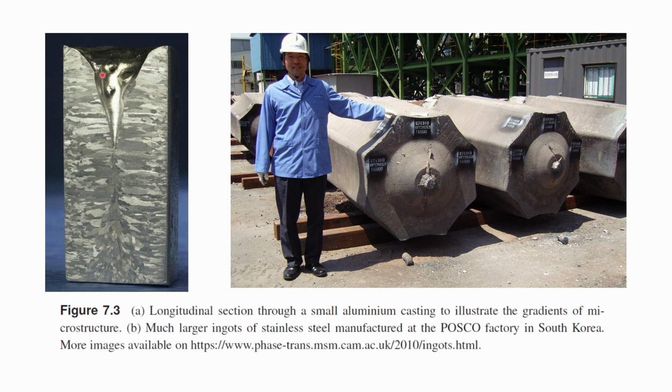The figure on the left here shows one example for aluminum materials, a product made by the casting process. You can see there are 3 layers roughly, and this middle layer is clear. Also, you may notice on the top part there is material missing. The reason for this is the phase transition from liquid phase to solid phase, which is linked to shrinkage. Same material, same mass, the liquid phase has higher volume and the solid phase has lower volume. That's why along this part you have the transition finished. There's the middle part when it transfers from liquid phase to solid phase. There's not enough material to fill the gap, fill the space. That's the reason we have this part.